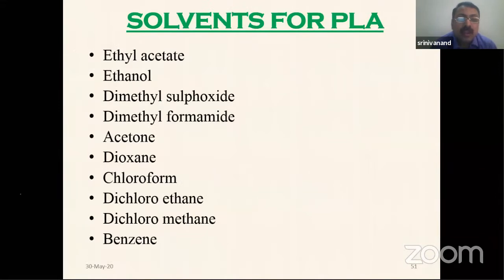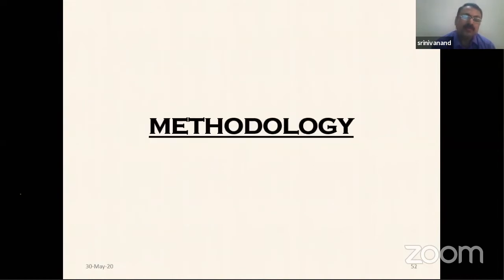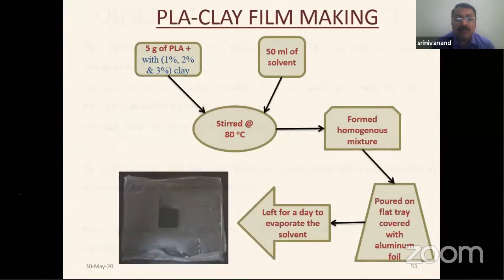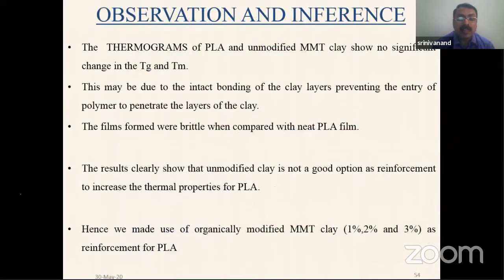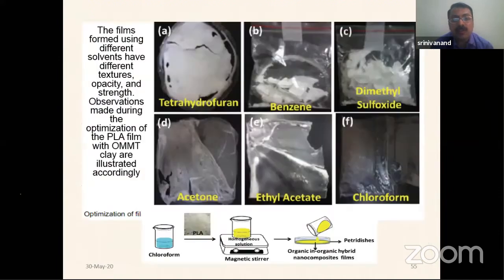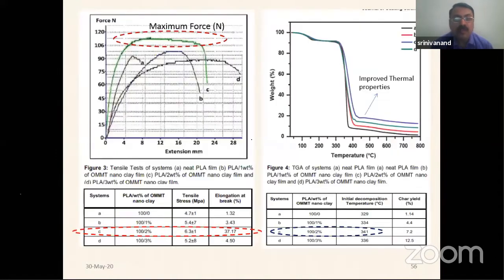These are the solvents that I have tried with PLA. The ideal solvents for PLA could be ethyl acetate and ethyl alcohol, because we don't want to use chlorinated solvents. That's why we preferred ethyl acetate and ethanol. In rarest of rare cases we have used chloroform. This is how the films were made, and we did the thermal studies. As you can see, with ethyl acetate and chloroform the PLA forms an excellent film.